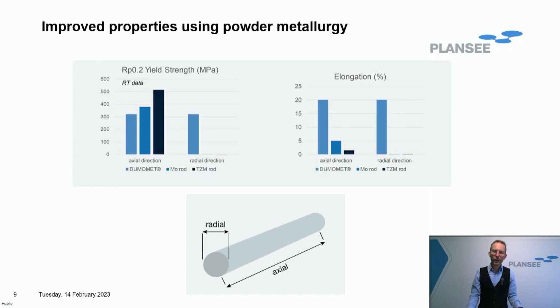On these two graphs, we show the yield strength and the elongation of different molybdenum materials depending on the direction. A regular forged molybdenum rod has almost 400 megapascal yield strength in axial direction, but a very low strength in the radial direction. Similar behavior you can see with elongation on the right side.